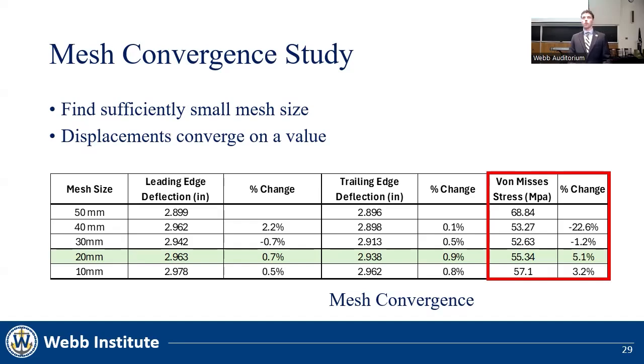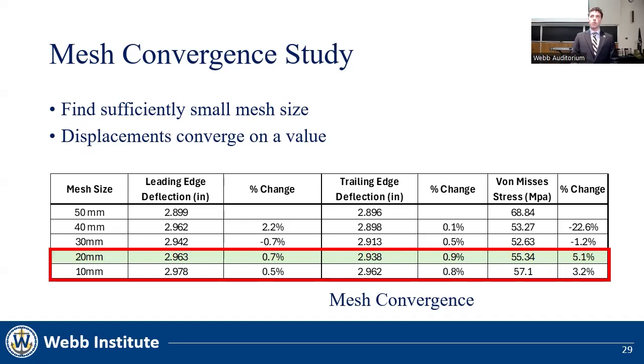And the right two columns show the maximum von Mises stress, as well as a percent change from the previous mesh size. Between a 20 millimeter and a 10 millimeter mesh size, the percent change in the leading and trailing edge deflections were both under 1%, while the percent change in the maximum stress was only 3.2%. This meant that a 20 millimeter mesh size was sufficiently small to perform an accurate analysis. For reference, when moving between a 50 and a 40 millimeter mesh size, the change in the maximum stress was 22.6%.